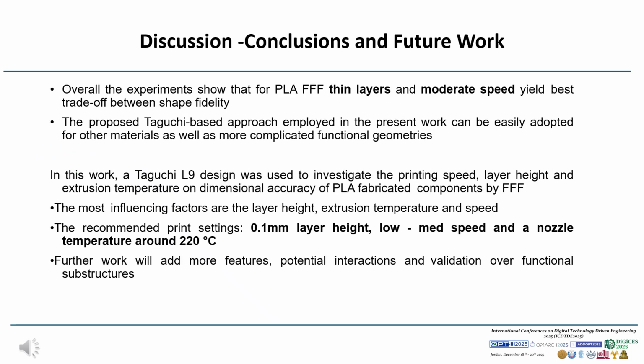Our experiments indicate that thin layers combined with moderate printing speeds offer the best compromise between dimensional fidelity and build time for PLA FFF. The Taguchi-based methodology we used here is quite general and can be applied to other materials, geometries, and even other additive manufacturing processes. To conclude, this work applied the Taguchi L9 design to study how layer height, printing speed, and extrusion temperature influence the dimensional accuracy of PLA parts produced by FFF.